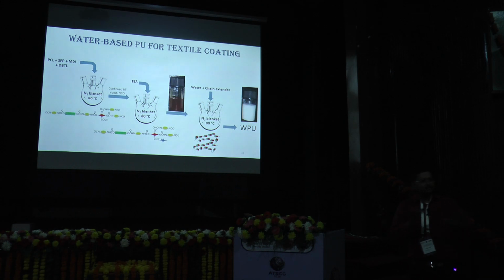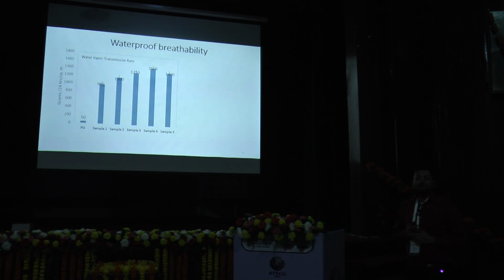So you just apply polyurethane on fabric by coating method, and then you will end up with antibacterial properties which are durable till this polyurethane stays on fabric. It's like the life of that coated textile. Then we have tested whether it is waterproof or not and whether it is breathable or not. So we have found the polyurethane layer is highly breathable. It gives us a hydrophilic path through which water vapors coming from the body can pass through, but liquid water coming from outside cannot come in. So that is called breathable waterproof kind of applications.